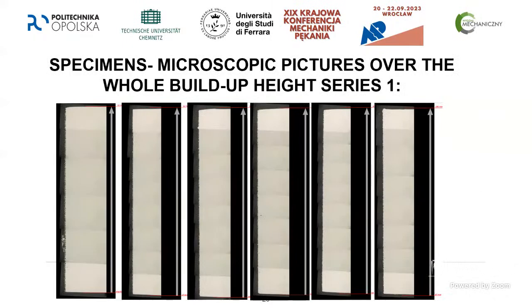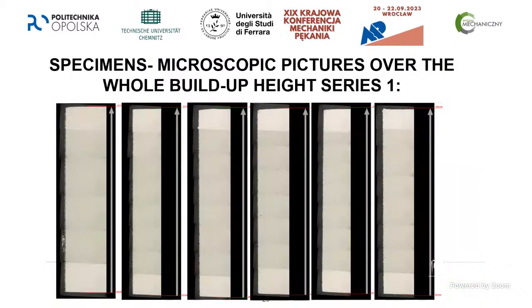So besides this, our partners also gave us information. As they printed it in Chemnitz, they also performed microscopic pictures of the whole build. For the full samples, you can see that we really had no pores in the specimens, almost perfect. In the second case, I have chosen some pictures. There were more pores in regard to the whole printing process. So maybe this could also influence the fact that we didn't have the cracks exactly in the middle, but that shouldn't be the case for all specimens, because this happened for all specimens.